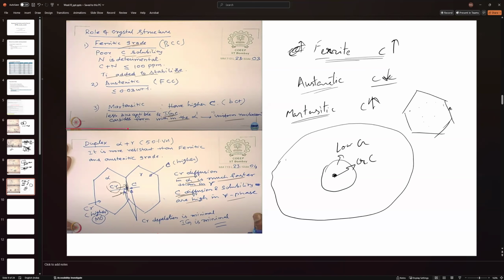Still, the rest of the grain is rich in chromium, right? This is a small area. So what will happen from this chromium-rich region? Some of the chromium will diffuse toward this region, and this is your grain boundary. So just imagine this is the grain boundary, this region around that. When this chromium diffuses to this region, you again have sufficient chromium concentration, which again gives you the passivity due to chromium, thus stabilizing it. Doesn't allow IGC. So if you have higher diffusion, you actually prevent intergranular corrosion.